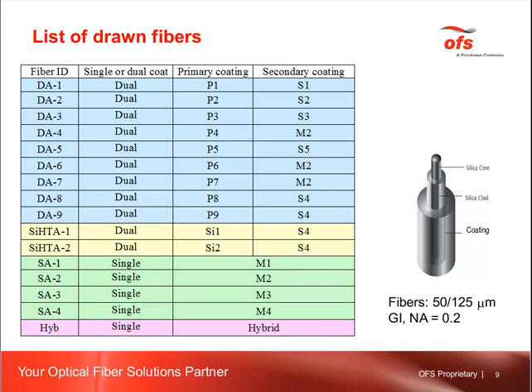The coatings DA1 up to DA9 are dual coatings. Two fibers also had dual coatings, but they belong to sort of a special class. They use silicone acrylate as a primary coating, SiHTA1 and 2. And there is a series of fibers we drew with monocoats, SA1 to SA4, and also a hybrid formulation was used as a monocoat. On the right part of this slide, you see the waveguide we selected. So all these coatings were applied on a fiber with a graded index 50 micron core, 125 micron cladding, numerical aperture 0.2.